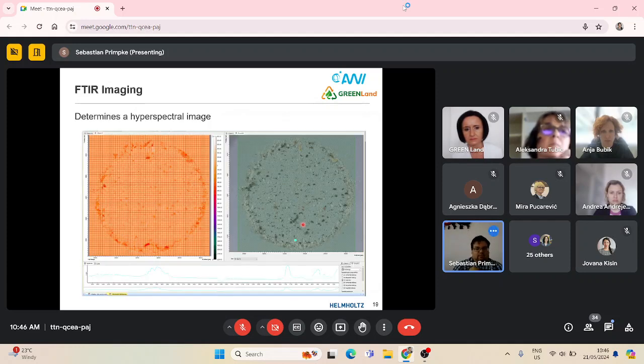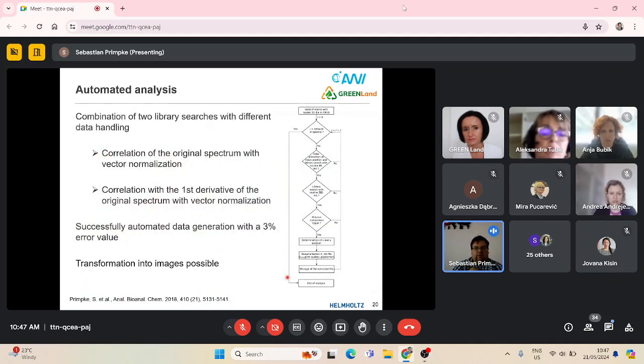We spent quite a lot of time in the beginning manually clicking at highlighted areas in these fields, then checking each spectrum manually. But we said early that this is too slow, and in 2018 we published our so-called automated analysis, which is currently still the basis of the analysis we're using, while we also still look for improved methods. We use a correlation with the original spectrum using vector normalization. The second step is to match a second time using the first derivatives and vector normalization. Only if both yield the same polymer type identified do we count it as identified. Otherwise, it is not discarded, because it could be something different.